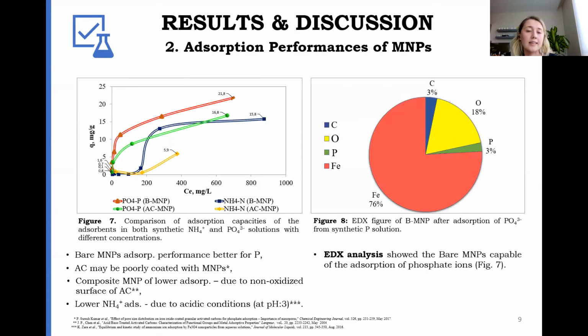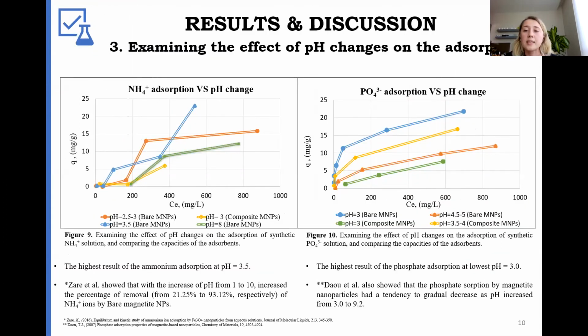I'm sorry. Well, we also have the result of EDX analysis. Here you see the EDX analysis showed the bare magnetic nanoparticles are capable of the adsorption of phosphate ions. Here we see the effect of pH changes on the adsorption processes. Ammonium adsorption resulted the highest at pH 3.5, but as seen, those are already close to each other.